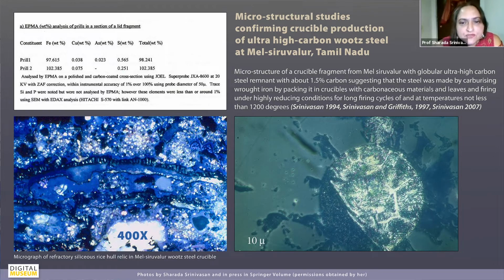This is also to show you that the analysis was done by electron probe microanalysis to confirm the composition. Another aspect was that the wrought iron was packed with the carbonaceous material, but the crucible also had to be highly refractory to withstand the very high temperatures you would have needed for this process, about 1200, at least, if not 1300 degrees centigrade. The crucible was also packed with coked rice hull relics, which contributed to the siliceous nature of the refractory.